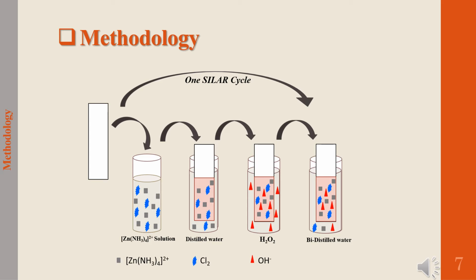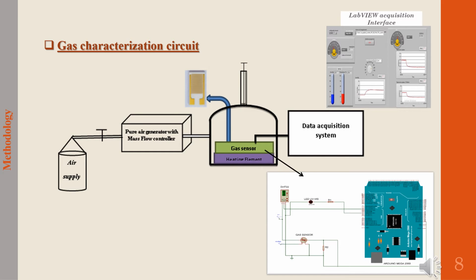The films prepared are thermally annealed at a temperature of 400 degrees C for an hour with a heating rate of 5 degrees C per minute under ambient air. The measurement system consists of three parts. The first is the sampling part, where the equipment is set for air generation and control. The second is the measuring part, which consists of the cell where the sample to be analyzed is injected, and the last is the acquisition and processing part. In our case, we use an Arduino Mega card with the LabVIEW program.